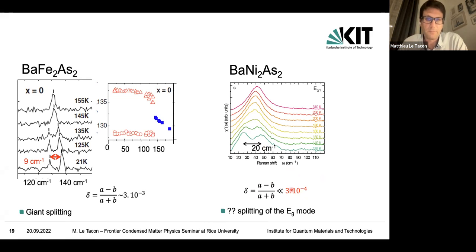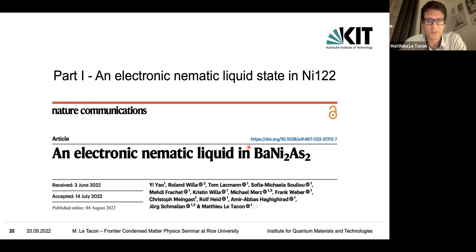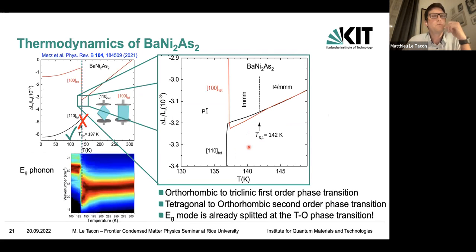So I'm there now with my parent compound, which has this very tiny distortion, and I have this insanely large splitting of the mode. And if I now take into account the fact that the mode is much softer to start with, that's almost 50% of the mode frequency splitting. So that's absolutely unacceptable. But that makes it interesting. And that's what gets us to the first part of the story and how we got to the notion of a nematic liquid in that system. So again, we've been comparing that very carefully with the thermodynamic measurement, because this is the point where we got a bit nervous.